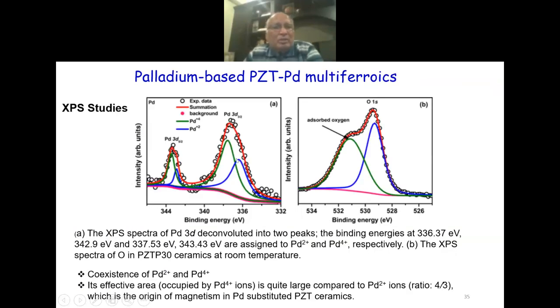To be sure that we do have the Pd4+ and Pd2+ in the material, we did XPS studies. And the XPS studies did show that yes, there were both of them. Actually, one is Pd4+, you can see Pd plus 4, and this is Pd plus 2, the spectra. And this is what we observe, which is the resultant of the two.